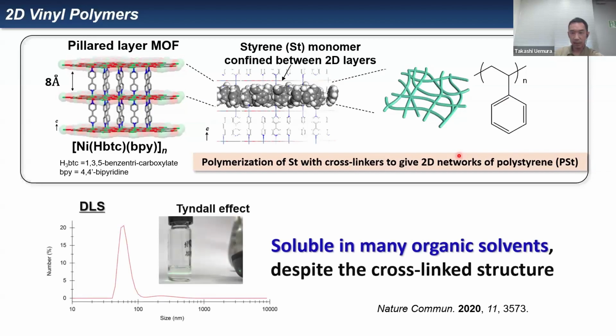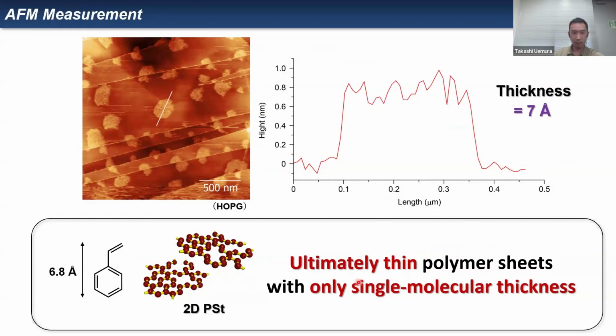And then next, yes, we checked the DLS because interestingly, this obtained cross-linked polystyrene was highly soluble in many solvents, even though it has a cross-linked structure. So next, we checked the AFM and found the formation of ultimately thin polymer sheets with only single molecular thickness. So this is the first synthesis using commodity polymers, such as polystyrene, achieving the formation of ultimately thin, single molecular thickness polymer sheets.